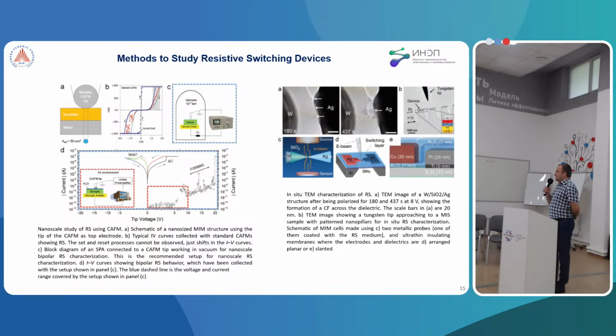The next method of studying resistive switching is nanoscale methods. This is scanning probe current microscopy, presented on the left side of the slide. Schematic of a nano-sized memristive structure using the tip of the current AFM as a top electrode. On B, we present typical current-voltage curves collected with the standard AFM tips, showing the resistive states. On C, we present a block diagram of the connection of the current AFM tip working in vacuum